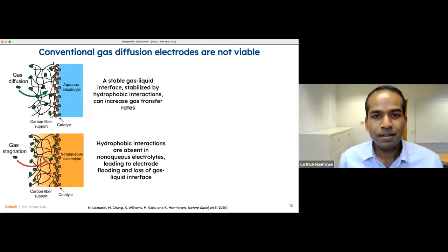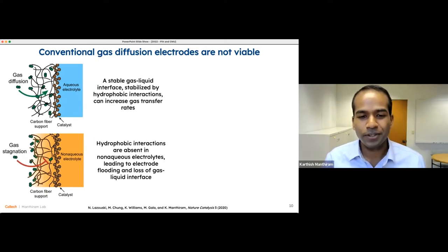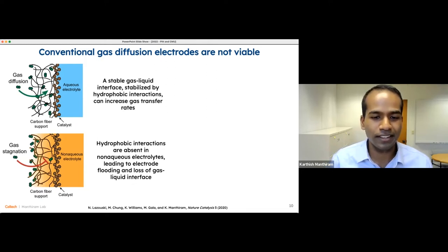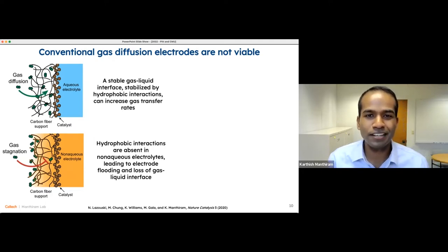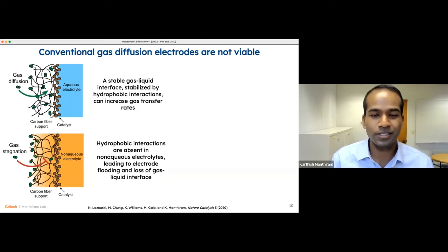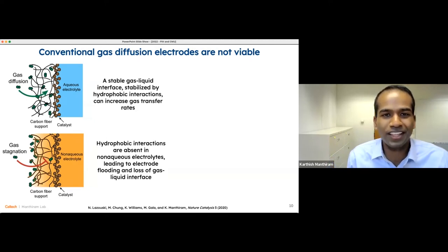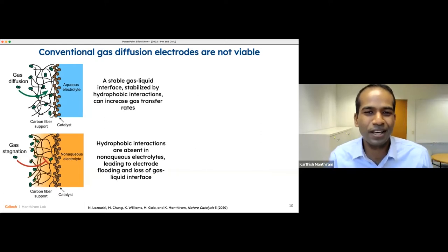Now, if we take that same carbon fiber-based electrode and we try to use it in our system, this non-aqueous electrolyte based on THF, it is entirely flooded. And that's what we found in our early studies, that THF loves to wet carbon fibers. It, in fact, even likes to wet PTFE. It is not repelled by PTFE. You can take a block of PTFE and put a drop of THF on it, and it will not bead up on it, which was honestly and intuitively what I had thought would be the case prior to that point.